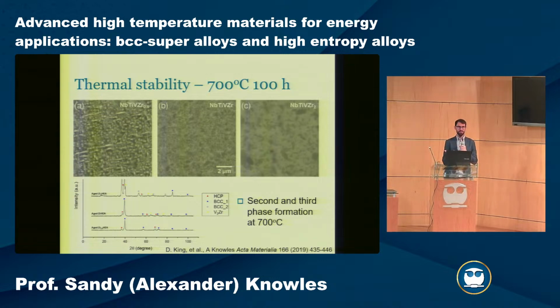So this could be a problem. We've failed at creating a single phase high entropy alloy. But when we think as metallurgists, the majority of materials we use do have multiple phases in them. So rather than something that is single phase, we now have a multi-phase material that is potentially a mechanism by which we can get high temperature strength and high temperature creep resistance, but also, as we talked about a little earlier, potentially interfaces as defect sinks. So this could have a good benefit in producing something that's radiation damage resistant.